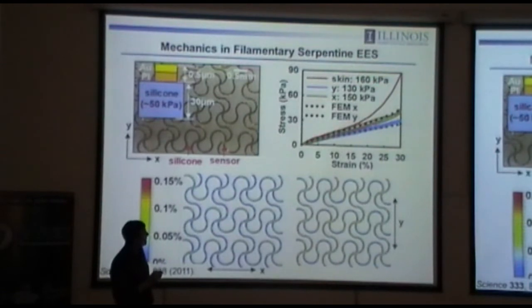160 kilopascal, roughly linear elastic response, up to about 15% strain, starts to go nonlinear, a higher effective modulus as you continue to strain, eventually rip the skin at about 30%. But if you look at the stress strain curves for deformation stretching along X and along Y for this integrated circuit, almost perfectly matched to the skin. That's by theoretical design that has these kind of properties, perfectly matched, but actually a wider linear elastic response range. If you look at the calculation, it's almost spot on with the experimental results.